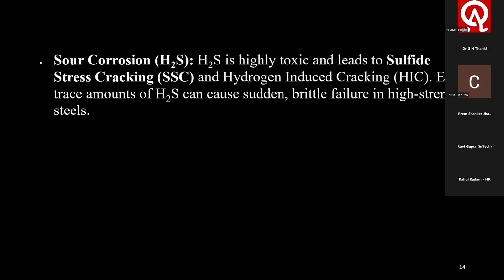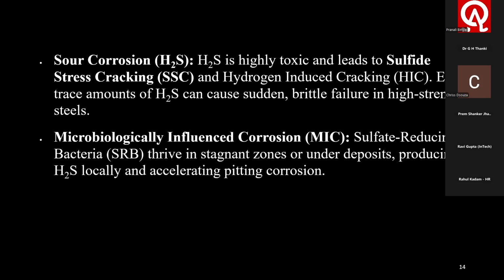Sour gas, H2S. H2S, that means hydrogen sulfide, is highly toxic and leads to sulfide stress cracking and hydrogen induced cracking. Even trace amounts of H2S can cause sudden brittle failure in high strength steels.